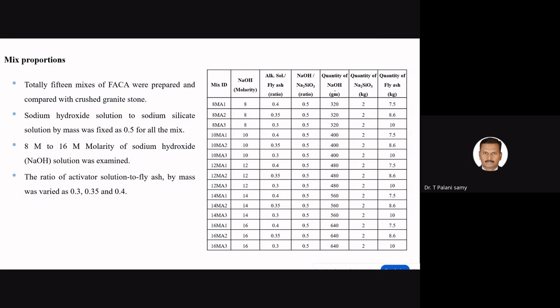For mix proportions, a total of 15 mixes of FACA were prepared and compared with crushed stone granite aggregate. The sodium hydroxide to sodium silicate solution ratio by mass was fixed at 0.5 for all trial mixes. Then 8 to 16 molarity of sodium hydroxide NaOH was examined, with activator solution ratios of 0.3, 0.35 and 0.4. The table shows the mix ID, NaOH molarity, alkaline solution to fly ash ratio, NaOH to Na2SiO3 ratio, quantity of NaOH, quantity of Na2SiO3, and quantity of fly ash used, tabulated here.